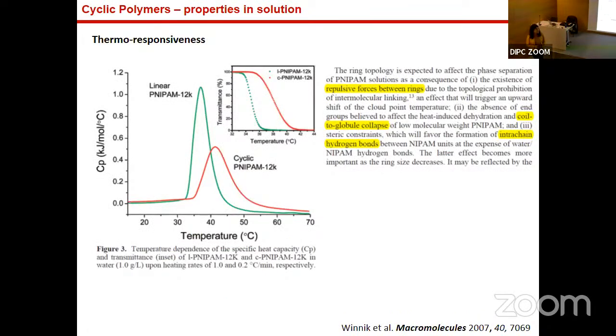Thermoresponsiveness. There are some polymers, like, for example, NIPAM, which is thermoresponsive. That means that when you heat a water solution of this polymer, it starts to become cloudy. It means that it doesn't like the water anymore. In this study, the cyclic NIPAM also showed that the temperature at which this process occurred was higher than in the linear one. This is the heating temperature, this is transmittance. At the beginning, at a low temperature, it is completely soluble, and then it starts to become cloudy. The researchers explain these results as a difference in the dehydration process and the formation of the coil to globule collapse, and so on.